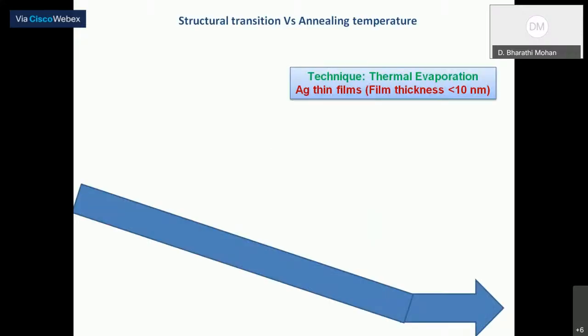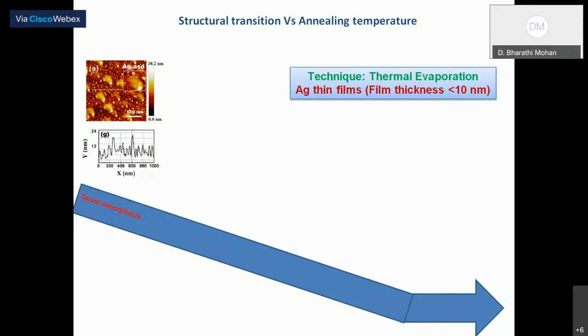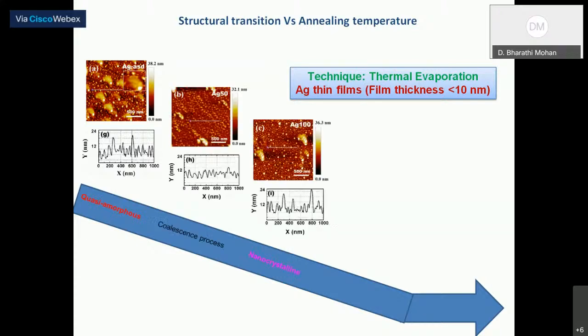Coming to the discussion of the fabrication and characterization of 2D SERS substrate, we have prepared silver thin films using thermal evaporator with a thickness of around 10 nanometer. And we looked at the structural transition as a function of temperature. This is the AFM image of the as-deposited silver film, which exhibits a quasi-amorphous state. And once you anneal at 100 degrees Celsius, it converts into a nanocrystalline state. And you can see the homogeneity in both size and shape, which is much better.